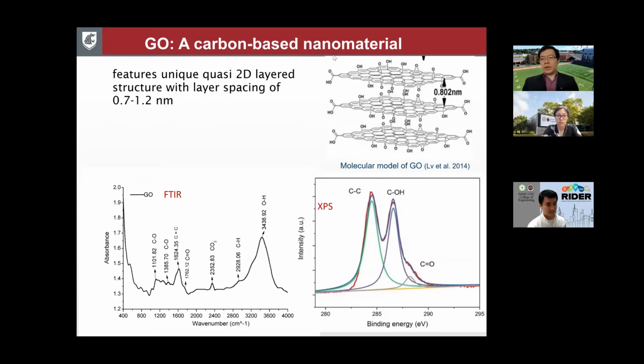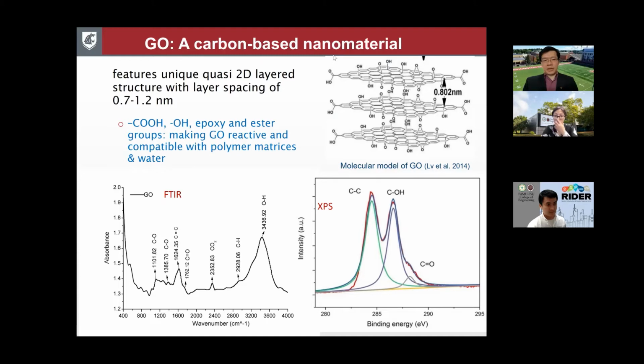Now, just to give you some idea about graphene oxide, it's a relatively new or emerging nanomaterial, which has been increasingly used in other industries, but in bulk applications such as asphalt and cement concrete, it's relatively new. Basically, this material features a unique quasi two-dimensional layer structure with layer spacing approximately 1 nanometer. As you can see from the Fourier transformation infrared spectroscopy on the left and the X-ray photoelectron spectroscopy on the right, basically these nanoplatelets carry a lot of surface charges on it, which mostly include carboxyls, hydroxyls, epoxy, and ester groups. And those make the graphene oxide very active and actually reactive as well, and quite compatible with polymer matrices and water.